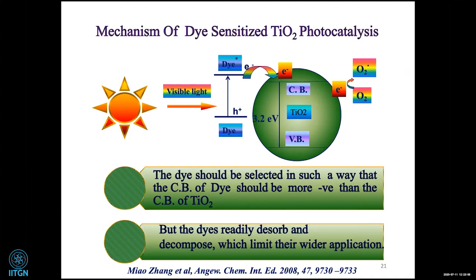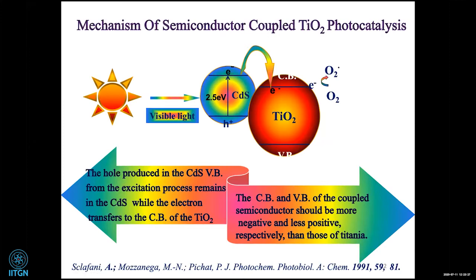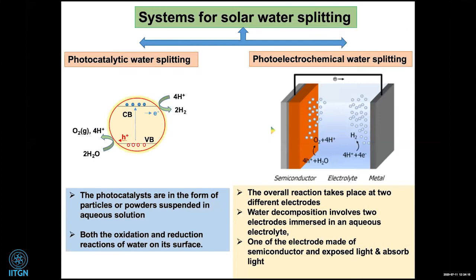Taking a cue from nature, you can combine with a dye — a small band gap semiconductor that quickly pumps electrons if the levels are suitable. The LUMO of the dye should be more negative than the conduction band of TiO2, so the electron will be quickly transferred. Or you can use a quantum dot like CdS, which has a 2.5 eV band gap. The main problem with sulfides is photocorrosion, which is why you need a sacrificial agent or suitable electrolyte. There are only four combinations: metal doping, non-metal doping, small band gap semiconductor, or dye replacement.